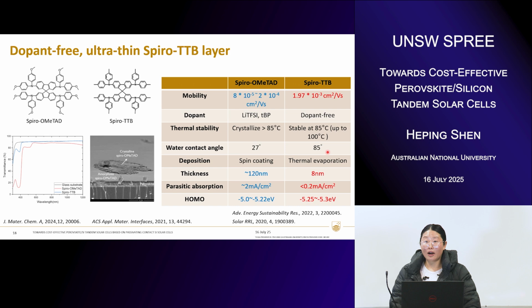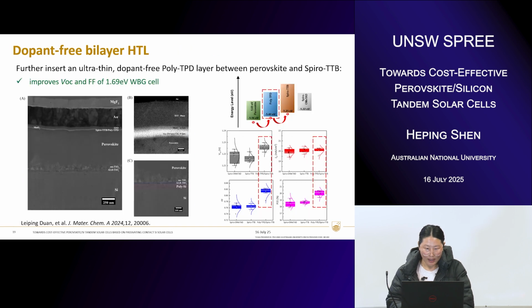And also it has a higher water angle that allows us to prohibit the penetration of moisture into the cell. And it can be deposited through the thermal evaporation method, the vacuum method, with which we can deposit an ultra thin layer. With that, we can minimize the perovskite absorption loss to a very low level. And its energy level is also found to be better, which I will share a little bit later. Okay, so that is our analysis and our justification for using this material in the tandem to replace spiro-OMeTAD.